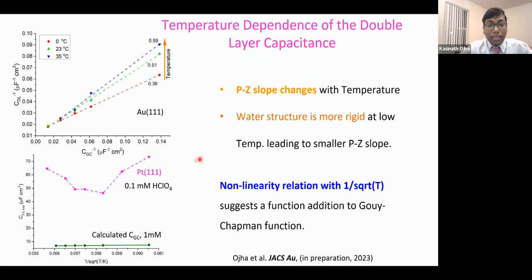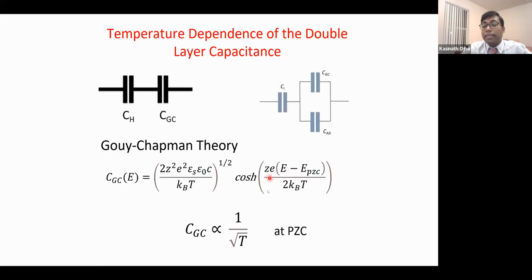And we did that. This is the capacitance at different temperatures, plotted against 1 by square root T. This is a calculated value at 1 millimolar concentration. Basically, this is a linear line having a slope. But if you look at the platinum double layer capacitance at all those different temperatures, it's not linear at all. It's going down, it should go down further, but instead, at high temperature, it goes up again. So that means there is some non-linearity there, and that suggests there are some additional capacitors that we add in the model, and that leads to the non-linearity, not really a Gouy-Chapman equation.